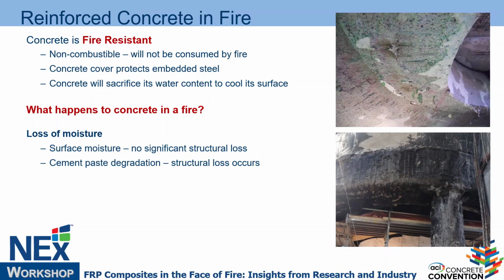We put fibers, right, in the high-strength concrete, polypropylene fibers. There was a question, how does that work? Well, these fibers, with elevated temperature, will basically disappear, burn, and create, if you imagine, tiny micro chimneys that vent the steam from the element and reduce that pressure, and that's how they can last. But again, as this concrete starts losing this moisture, after that it starts chemically changing and degrading, right?